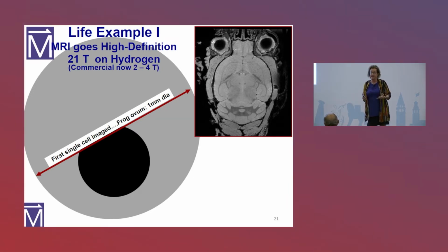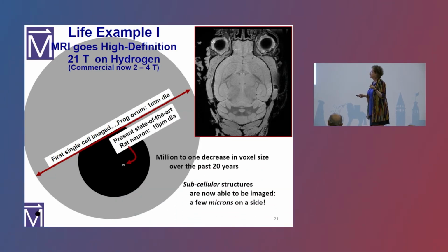Another reason is that you don't really want to go too much higher, because if you increase the magnetic field, you have to increase the RF field with which you're measuring, right? You have a resonance condition between the field and the RF field in which you do the magnetic resonance imaging. Typically you can see about a 1 millimeter resolution. But if you go up to what we can go up to, which is 21 Tesla, you can get to a 10 micron resolution. So you can see things much better.